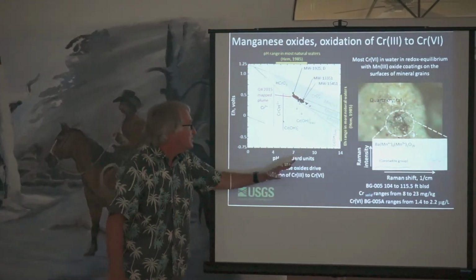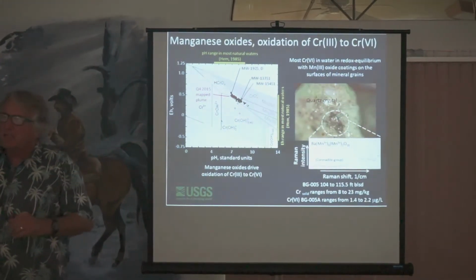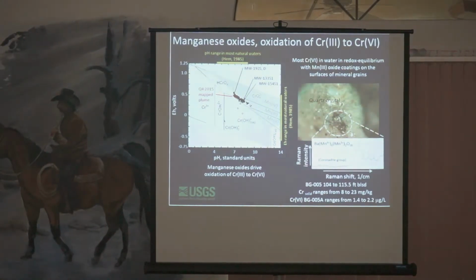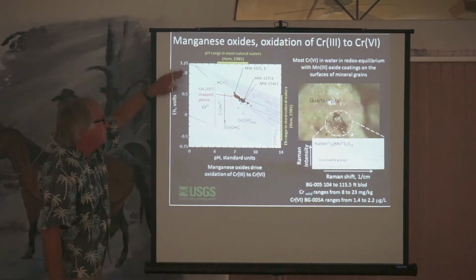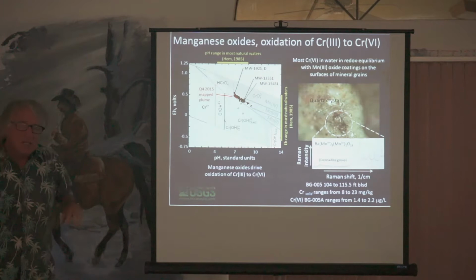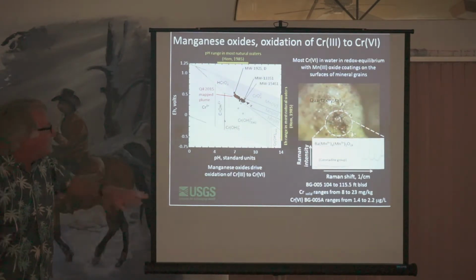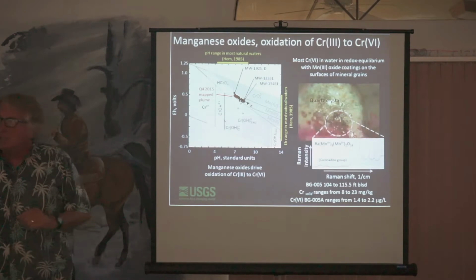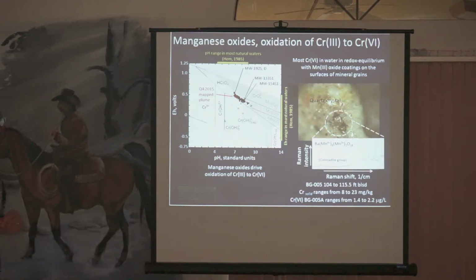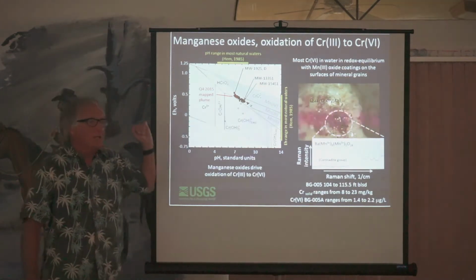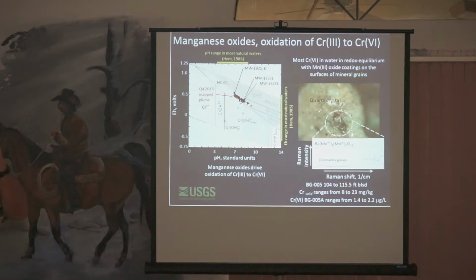This is what appears to be a very complex diagram. It shows pH on one axis, Eh on the other axis, which you could think of maybe as oxidation potential. Highly oxic here, oxygen present. Reduced here, oxygen not present. And what we're looking at is all the samples that we collected as part of the background study posted on there. And they're very tightly grouped. We calculated Eh from our Cr(III), Cr(VI) couple. We have very good, very well-behaved data. And we can make some interpretations from that data.